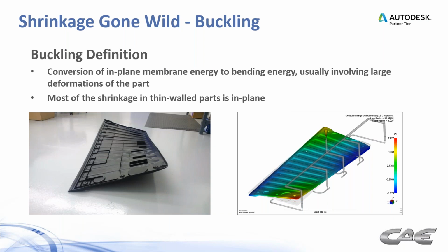Okay, and then the worst case scenario that we see with thinning walls out is buckling. I call it shrinkage gone wild. So the technical definition of buckling is a conversion of in-plane membrane energy to bending energy, usually involving large deformations in the part. Okay, what does that mean? Sounds pretty complicated. Membrane energy is energy in the plane of a given wall, and that membrane energy in plastics is shrinkage. It's the material trying to shrink, because that's what plastics do. And if those shrinkage levels are high enough with respect to the stiffness of the part, this part can undergo large deflections in the form of buckling. It just kind of springs out of position.